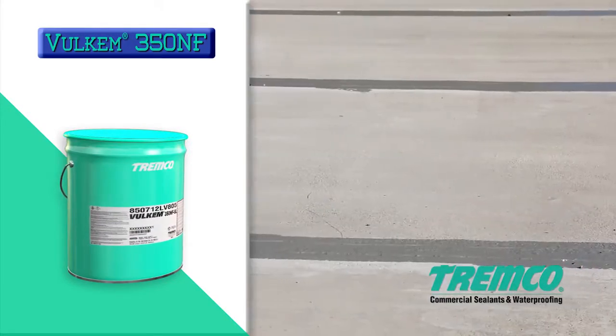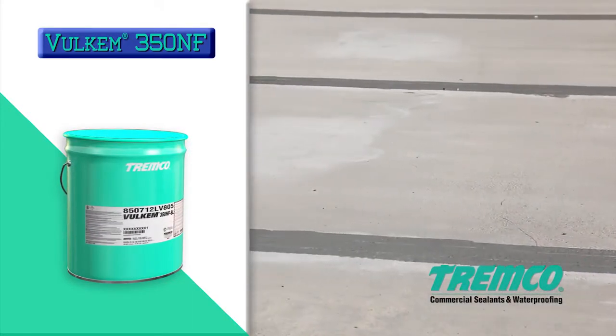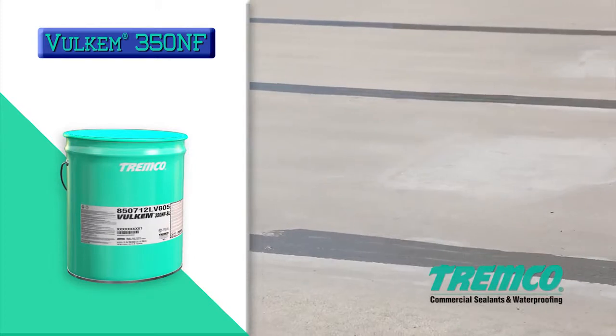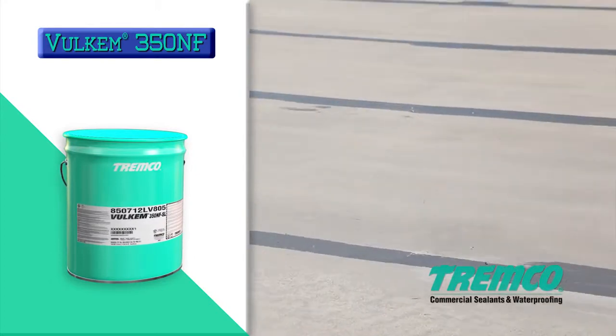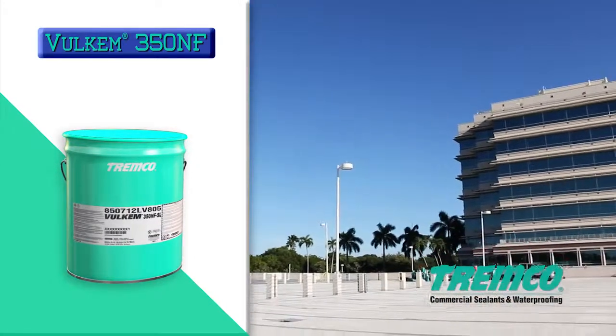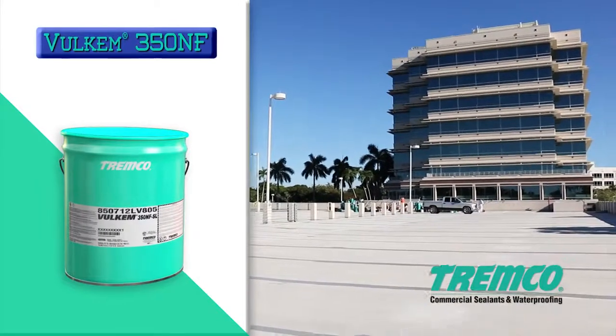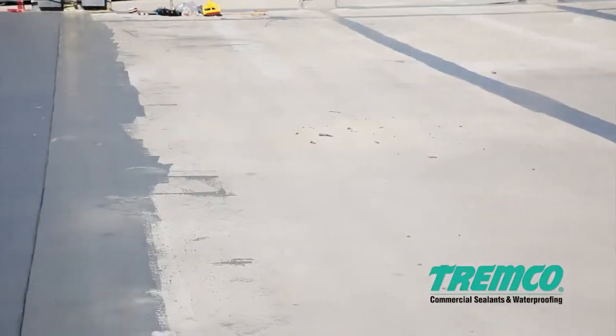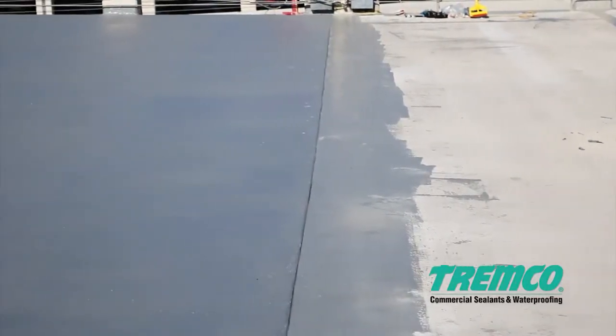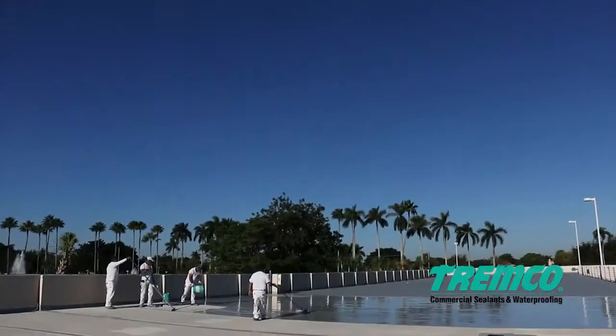Apply a 25 mil thick detail coat of Vulkem 350 NF roller grade 6 inches or 15.24 centimeters wide, centered over all untreated cracks, all routed and sealed cracks, and over all cold joints. Feather edge the terminating edge of the detail coat to prevent these edges from showing through the finished coating.